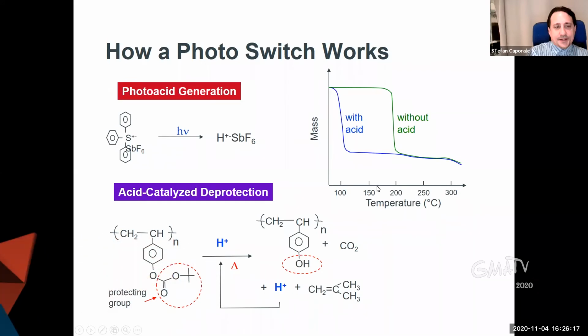And you can see there's an example of the mass of the film, and this is temperature in the x direction. With acid, as you're heating it, this will decompose and you lose your leaving group, but without acid, it's much higher. So as long as we process the wafer in the exposed areas in this process window here, we get a nice window that we can work in. You're not going to break down your PAG and your protecting group and make it soluble.